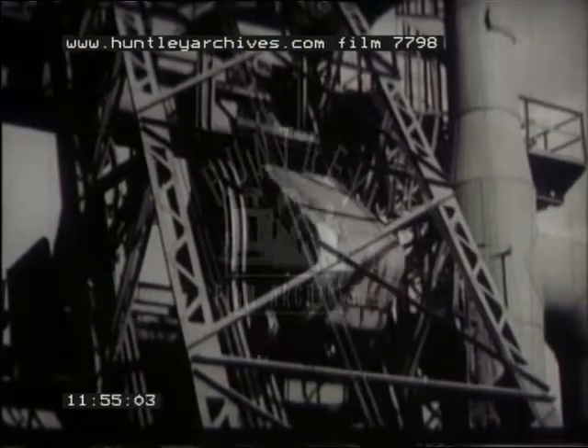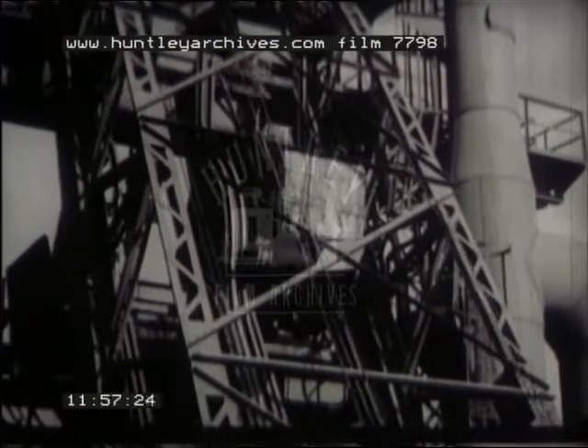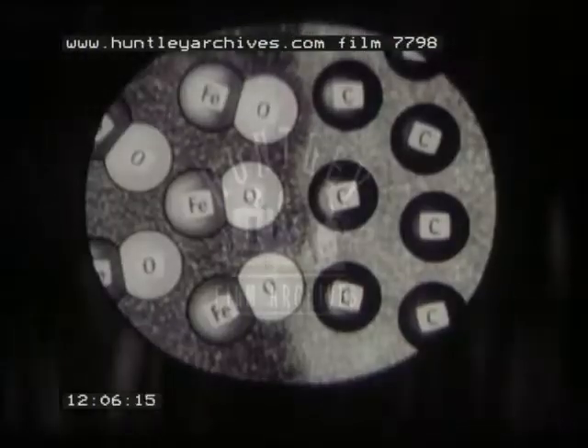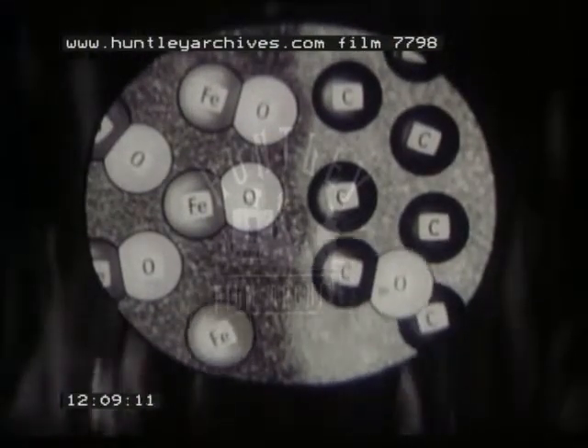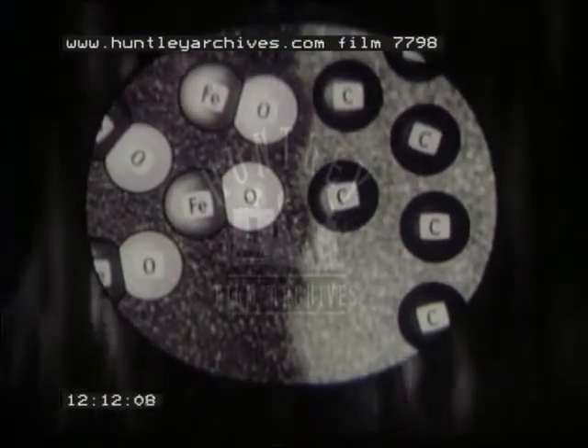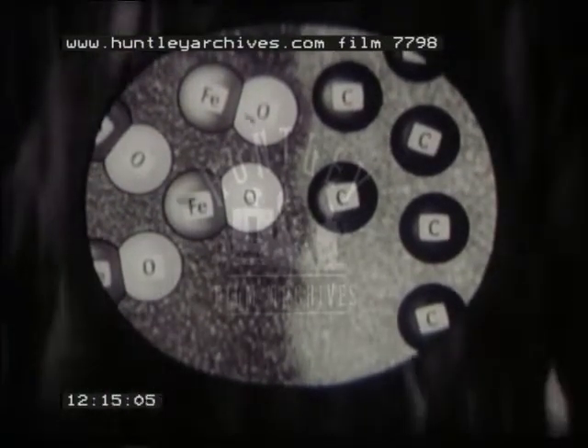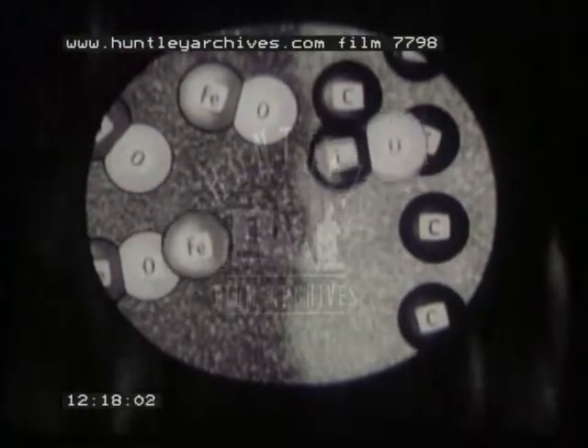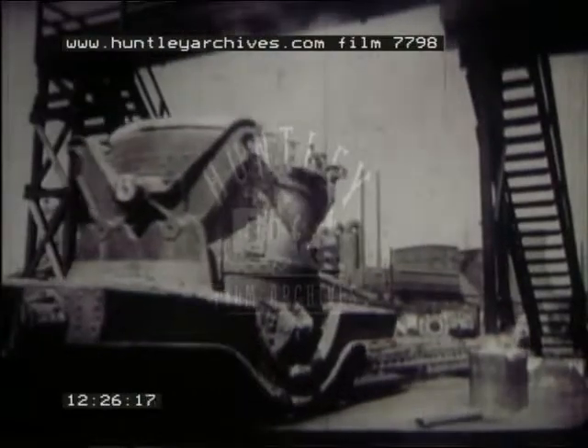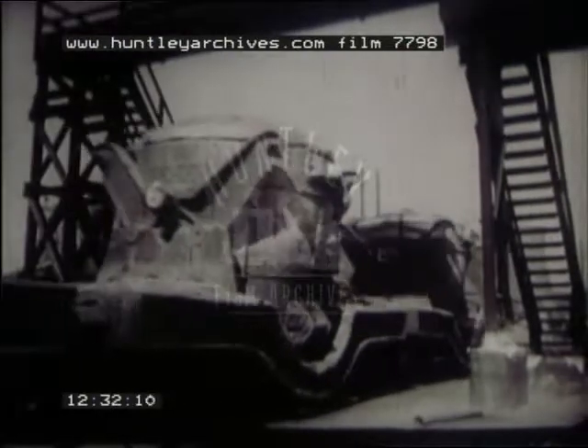We have seen how the raw materials, ore, coke, and limestone, are fed into the top. How the coke, burning in the hot air blast, heats the burden as it slowly slips down the furnace until it's hot enough for the chemical reactions to take place which transfer oxygen atoms from the iron to atoms of carbon. Often the molten iron is taken straight to the steelworks as hot metal. It's carried in big ladles lined with fire brick. These are then taken to the melting shop, where the hot metal is purified and is converted into steel.